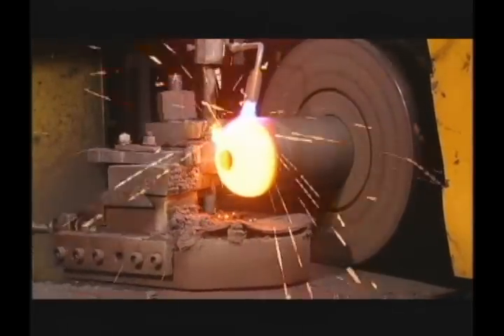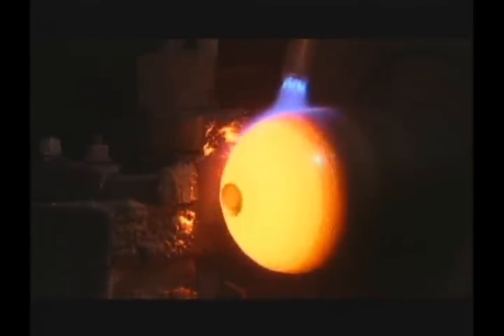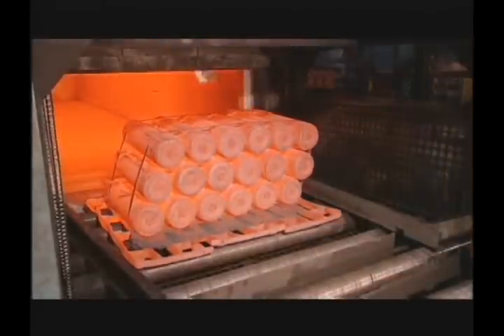The hot spinning process must be carried out with care and expertise so that folds or other defects are not introduced into the neck area of the cylinder. Shoulder profiles are normally hemispherical in shape, with the thickness approaching two to three times the sidewall thickness near the neck. Worthington cylinders are closed completely prior to heat treatment, which minimizes interior oxidation for a smoother surface finish.